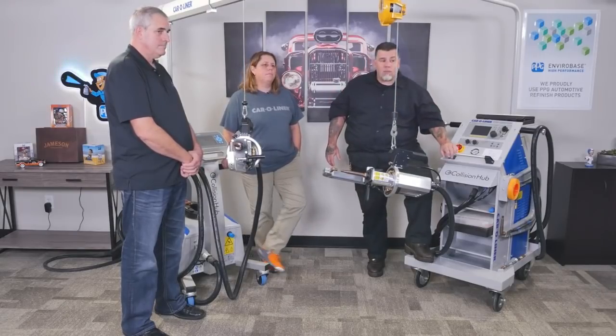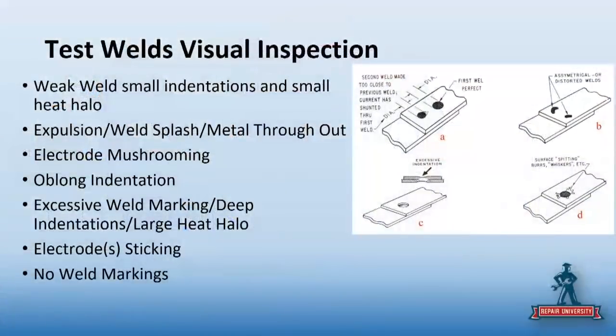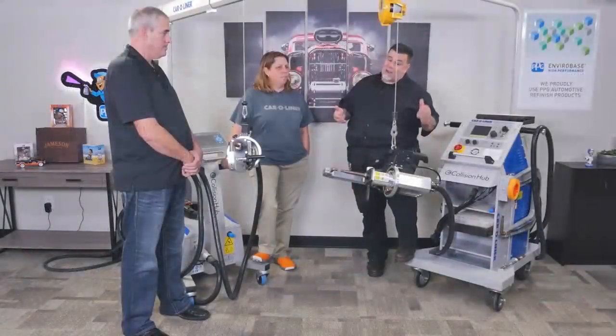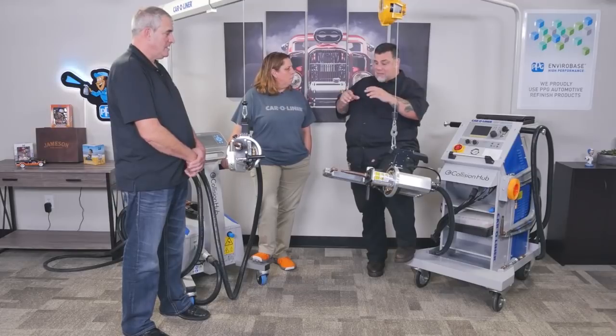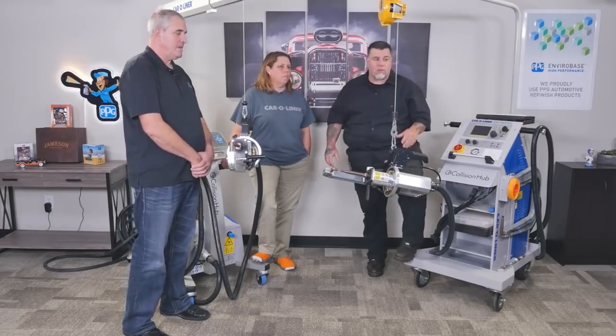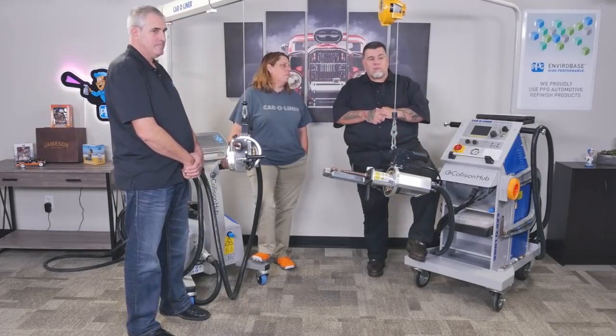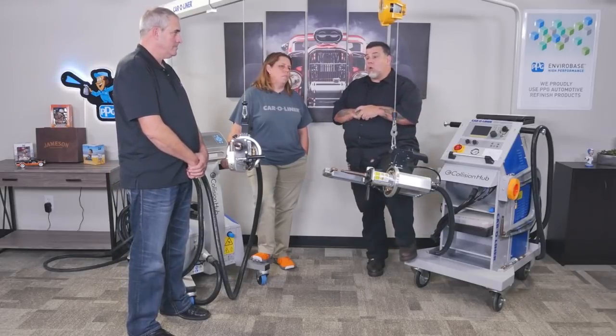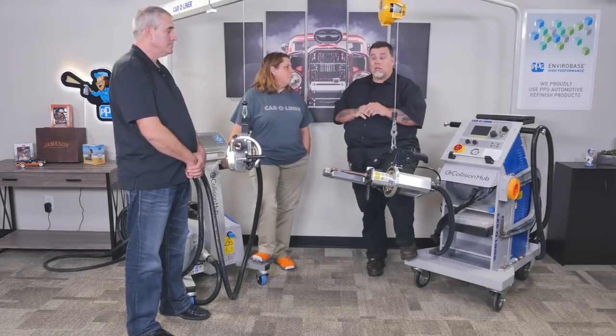Oblong indentation. Oblong indentation is usually from misaligned tips, or tips that are so badly used that only the left-hand center side and the right-hand upper side are making contact. Now you get this oblong, they're crossing each other. Excessive weld marking, deep indentations or a large heat halo: your machine's cranked up way too high for the type of material you're welding. And that's why we've got to set up the welder.